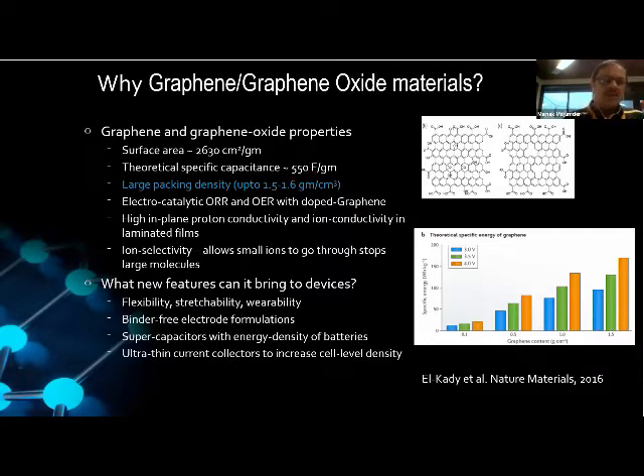The other advantage we have in graphene is that you can have a very large packing density of carbon, and you can go up to about 1.5 to 1.6 grams per cubic centimeter. In activated carbon, the maximum you can get is about 0.6 grams per cubic centimeter. This is actually a major advantage in graphene materials for making supercapacitor devices. As you can see in this figure from El-Kadi et al., if we can go to high packing densities of about 1.5, 1.6, we can really achieve energy densities close to 140, 150 watt-hour per kg, right? So that is one of the major advantages of graphene.